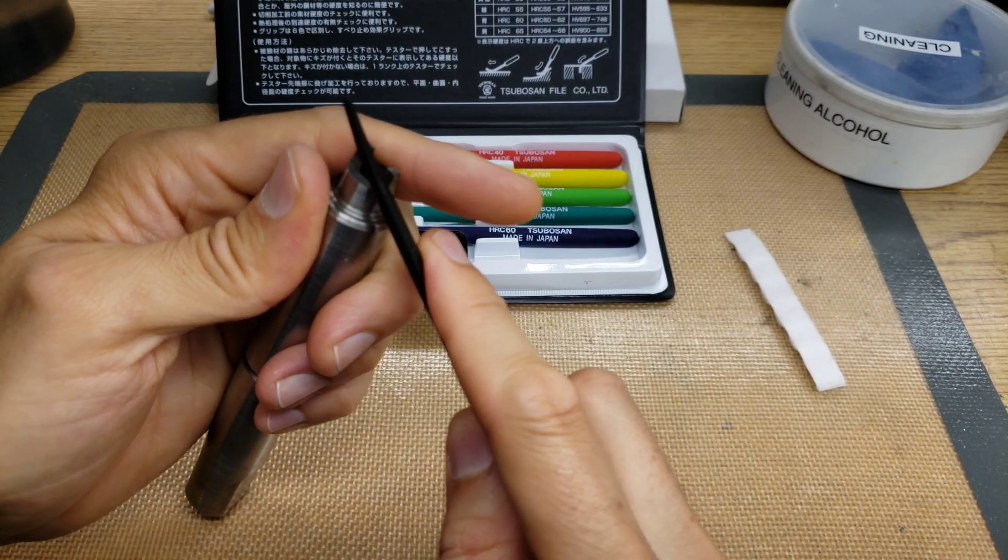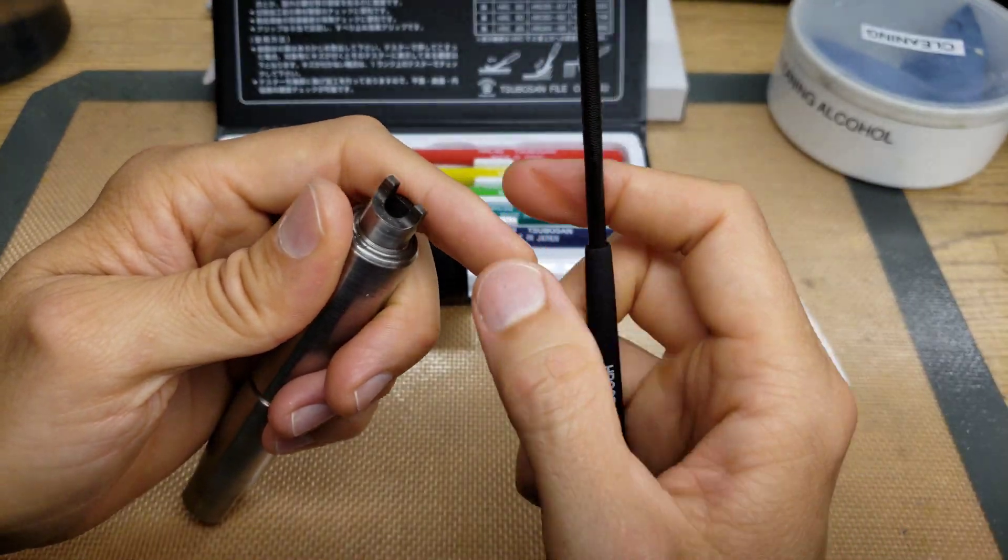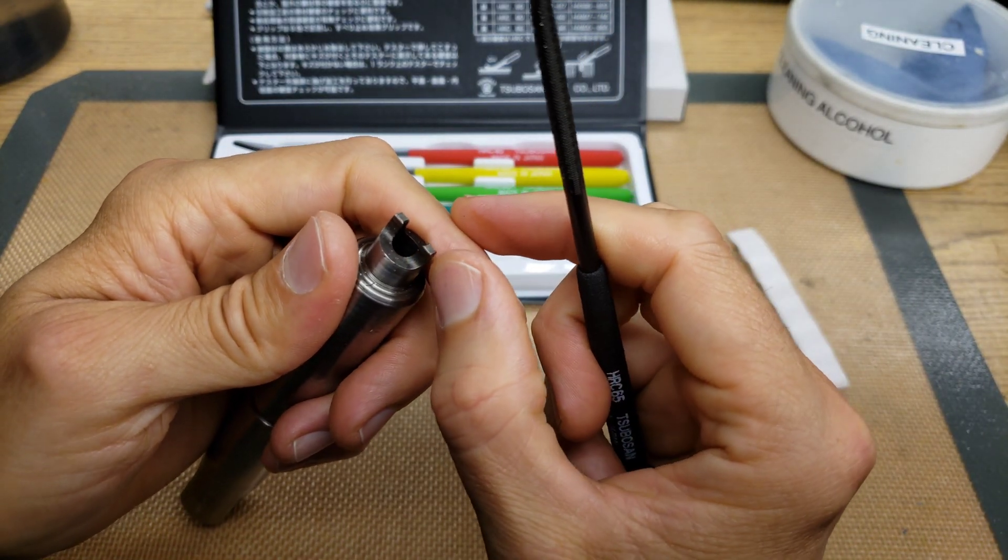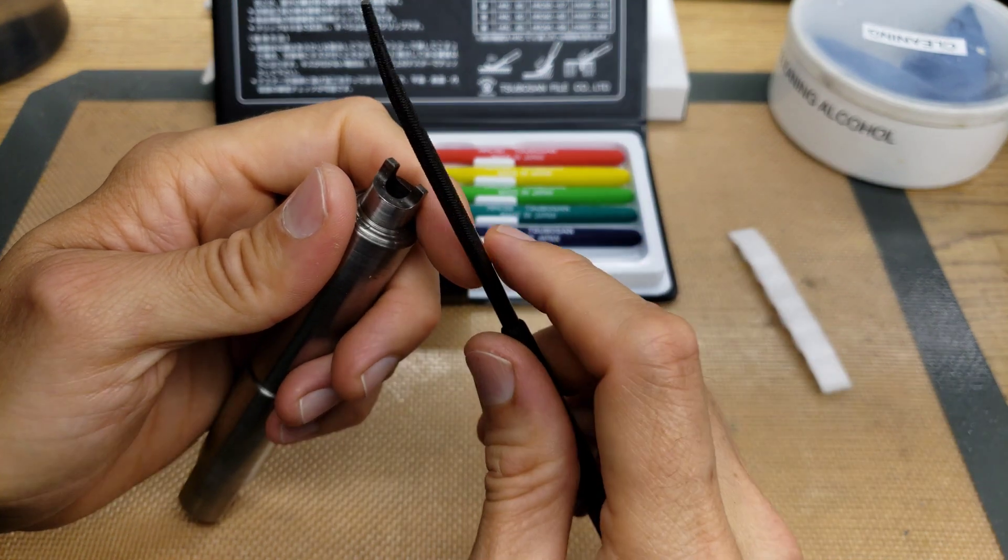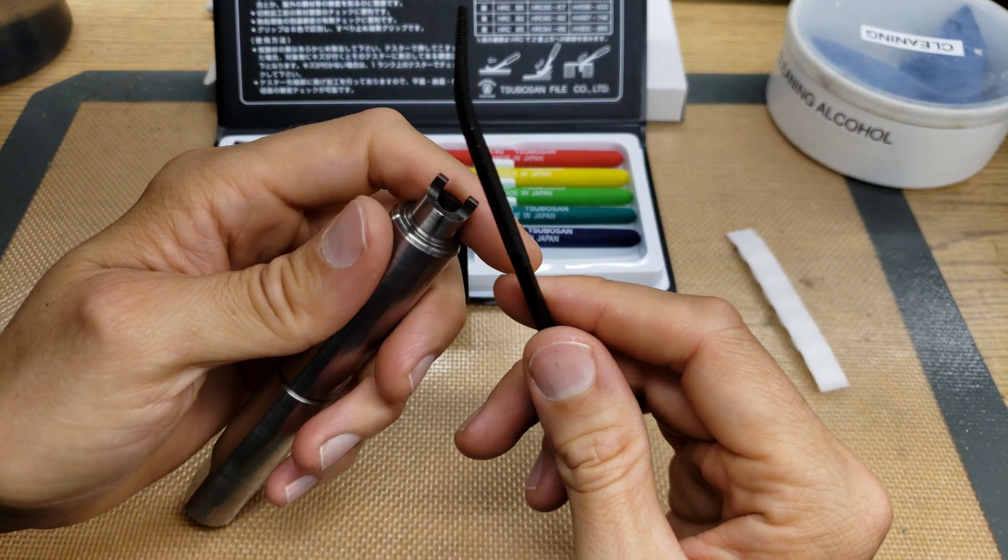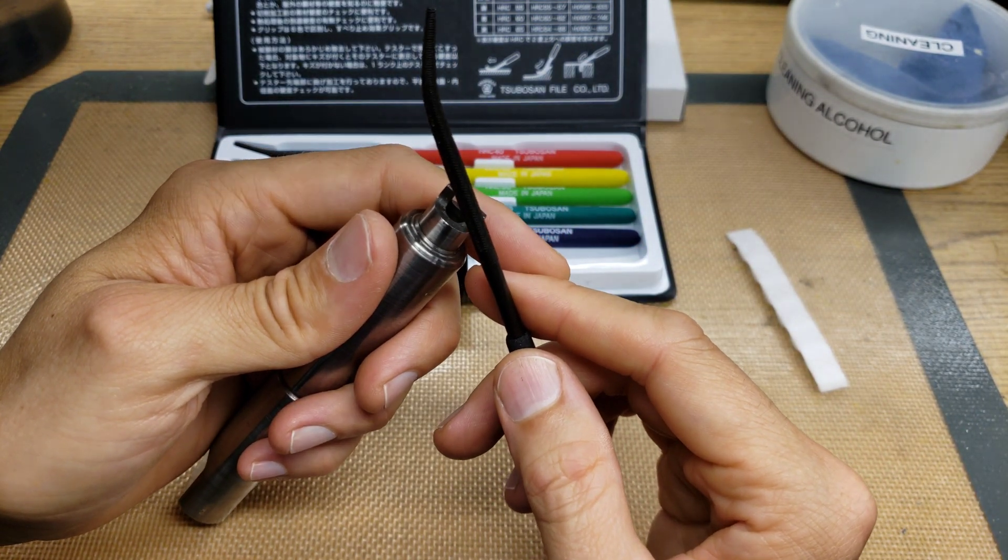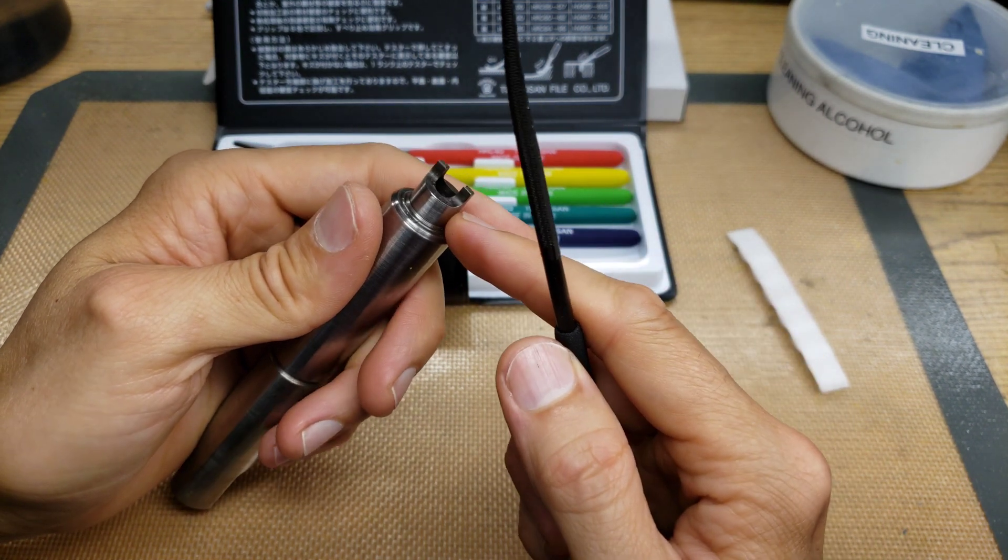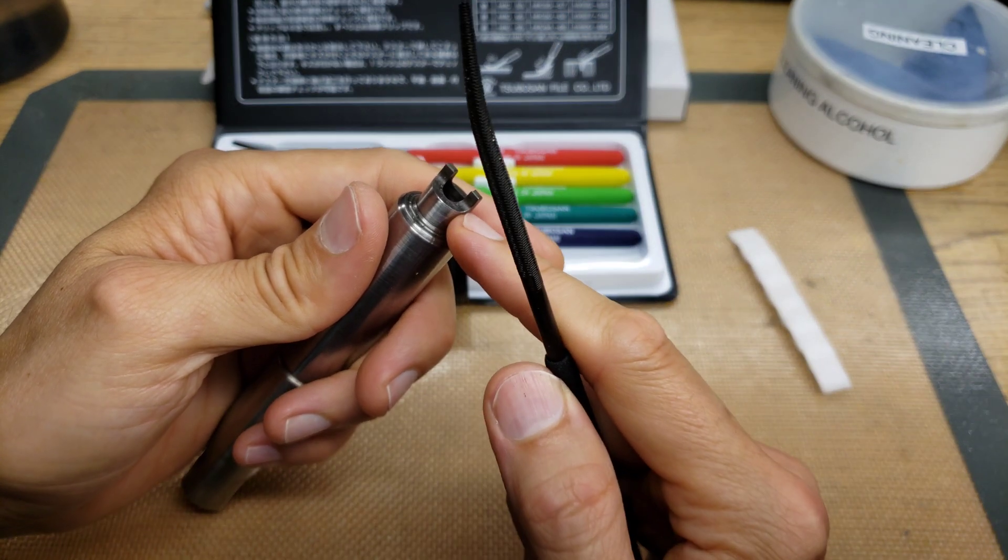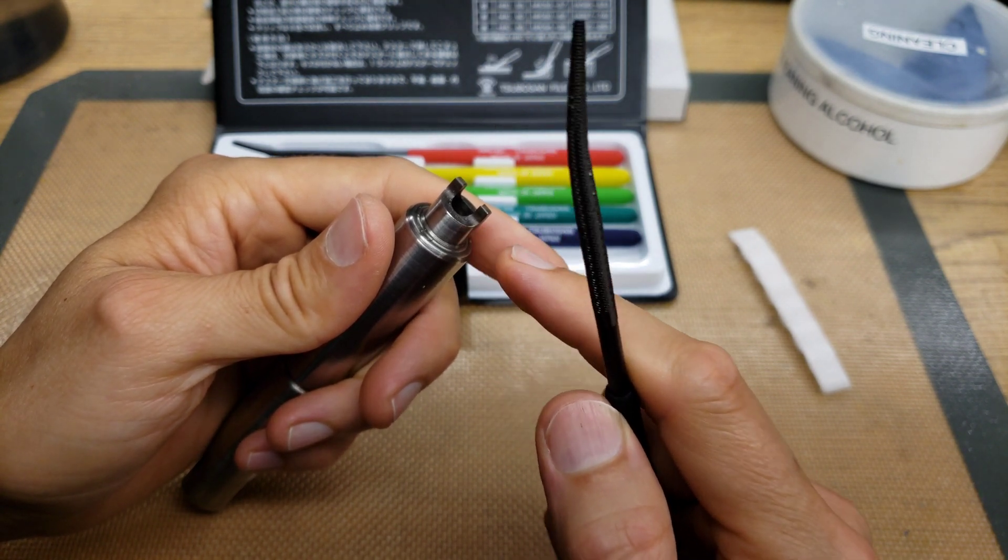Because of course the file is grabbing the edge and you feel it rough on the edge. So you have to do it like they have in these three little pictures on the case. Which is you have to try to do a flat surface, a curved surface, or at the worst a corner edge.